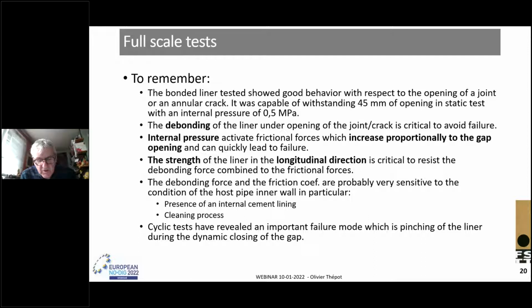The strength of the liner in the longitudinal direction is critical to resist the debonding force combined with the frictional forces. The debonding force and the frictional coefficient are probably, certainly, very sensitive to the condition of the host pipe inner wall, in particular, the presence of internal cement lining and the cleaning process.